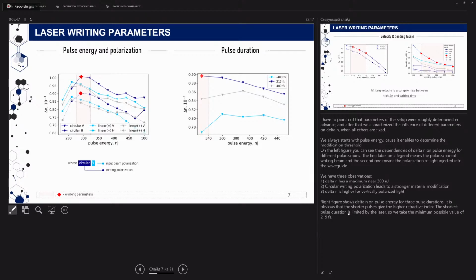We have three observations. Delta n has a maximum near 300 nanojoules. Circular polarization leads to stronger material modification, and delta n is higher for vertically polarized light. The right figure shows delta n on pulse energy for three pulse durations. It is obvious that the shorter pulses give the higher refractive index. The shortest pulse duration is limited by the laser, so we take the minimum possible value of 215 femtoseconds.